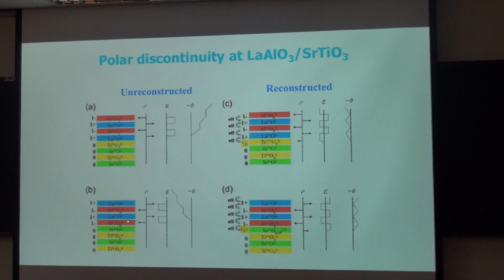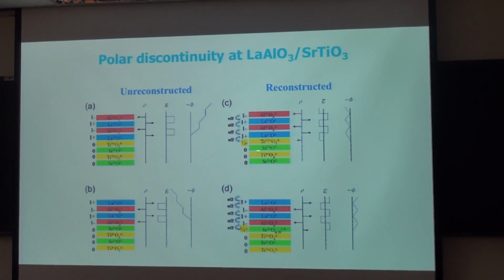The same situation is found for the p-type, that is the hole-doped case. But for the hole-doped case, we can find it is harder to change the valence state of oxygen. So these holes will be compensated by the appearance of oxygen vacancy. Therefore, for the p-type interface, the system is still insulating, but with the appearance of oxygen vacancy. So this picture gives an explanation why there appears a two-dimensional electron gas or conducting state at the interface of two insulating